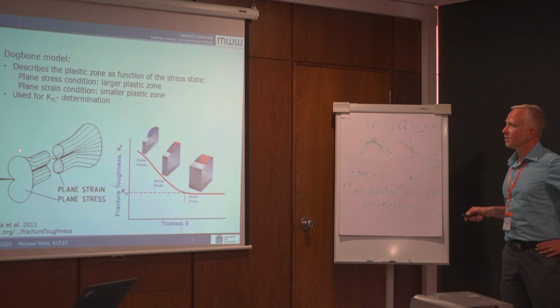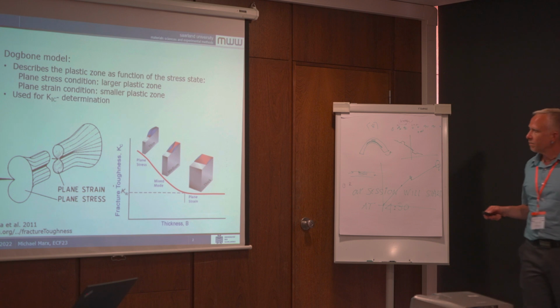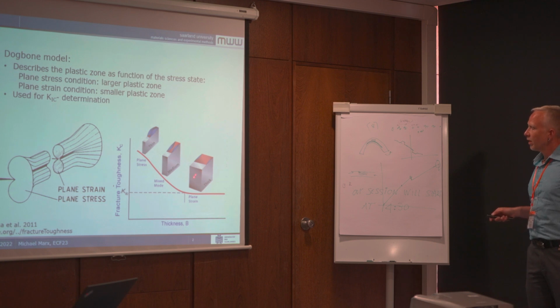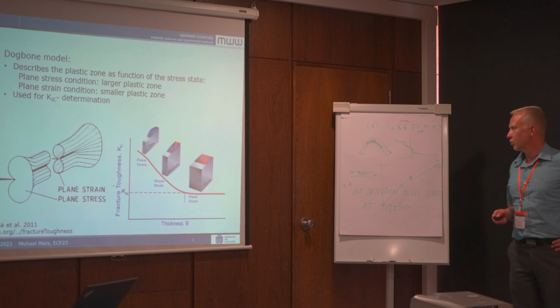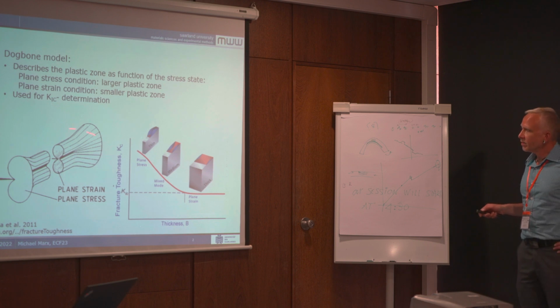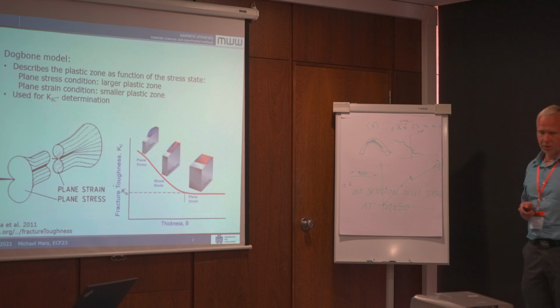middle and larger at the surfaces. This is very important if you determine the fracture toughness Kc for different thick specimens, because for a thin specimen the fracture toughness is higher than for a thick specimen, and only for thick specimens do you have a constant K1C value. This is related to the plastic zone. So what does this plastic zone look like?